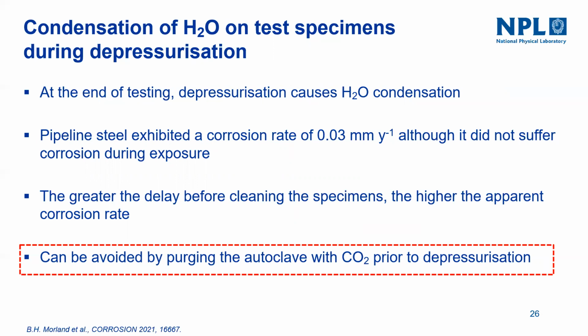These researchers have observed a corrosion rate of like 0.03 mm per year, although the specimen did not suffer any corrosion during the exposure. So what happens is, if you take more time to open the autoclave and clean, the contribution of corrosion from the condensation of water during depressurization will be more. How we can avoid this is by purging the autoclave with CO2 prior to depressurization.